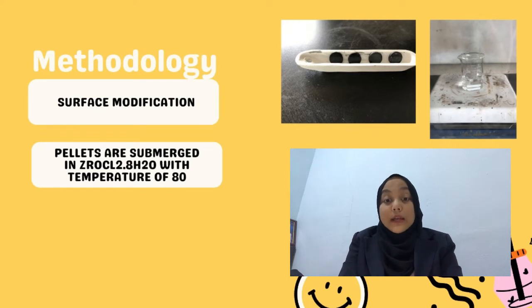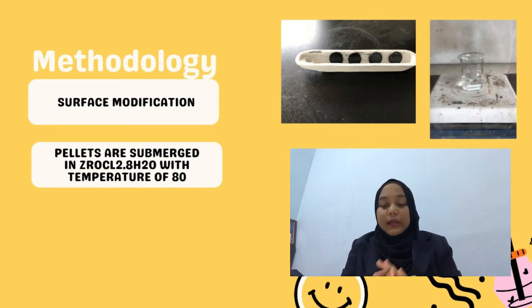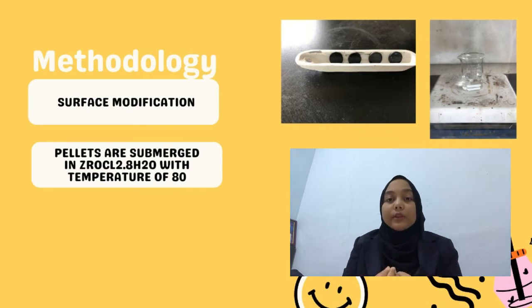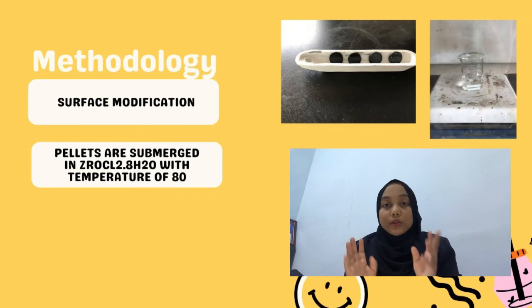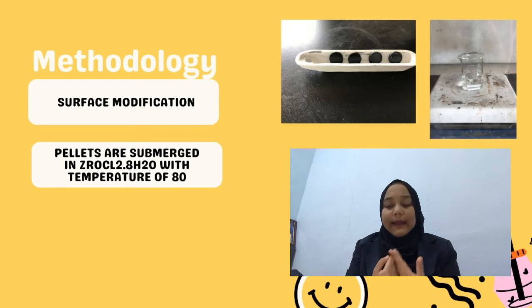The solution was then poured into a volumetric flask, which was shaken well to ensure its homogeneity. The pellet was submerged in the solution for 2 minutes. The submerged pellet was then dried at a temperature of 100 degrees Celsius for 2 minutes in the oven. Next, both pellets were coated with platinum, which acts as the current collector. The pellet was heated to 100 degrees Celsius for each coating in the oven, approximately 10 minutes.